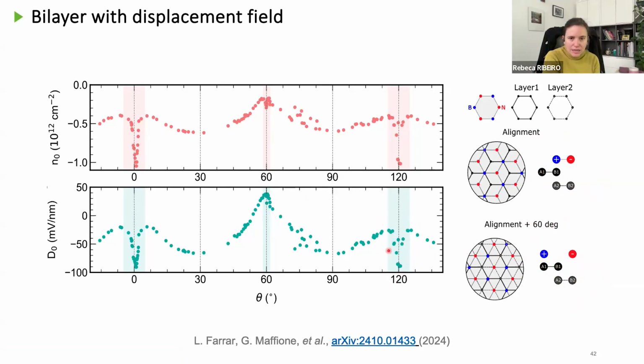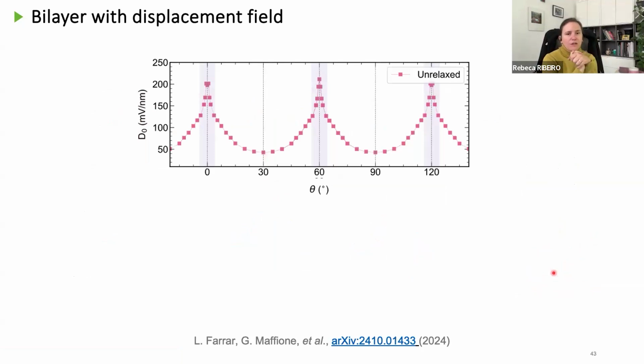Now, if you look at the big dips that I told you about and the small dips at 60 degrees, you might wonder, okay, but if it's coming from how the atoms arrange, what happens with graphene in the end, that they don't have the same lattice, but there is the commensurate state. So we asked our colleagues in Louvain-la-Neuve to make numerical simulations for us and calculate this intrinsic field. So how this intrinsic field should be, just thinking on atoms on top of each other, how they behave.